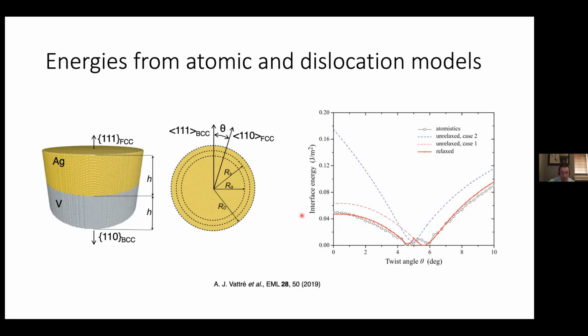And for the corresponding crystallographic character, using the dislocation-based model that I just told you about, we could calculate the interface energy. That's this solid, thick red line that you see here, which is our analytical prediction of how the interface energy varies with the twist angle. And as you can see here, we are quantitatively accurate in predicting this to within tens of millijoules per meter squared. So these are extremely accurate models that you can use to predict the energy of the interfaces as well as their internal structure, while basically circumventing atomistic models. So this is one way that you can describe interface properties using dislocation models.